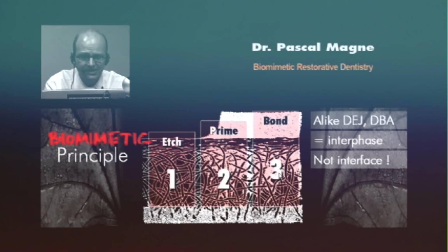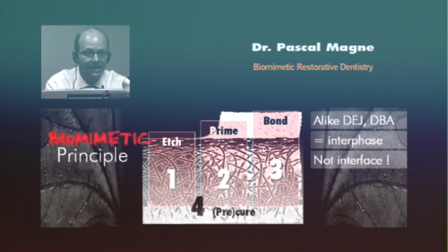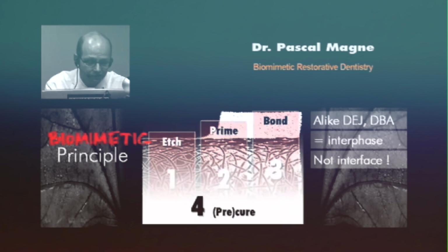Now, you can't mix these 3 in the same bottle. Of course, you can, but what you will get is kind of a salad dressing that is not going to work as well as if you use each of these products independently and separately. And there is a 4th step. I told you 4th step. What is the 4th step to successful bonding? It is the use of light, pre-curing the adhesive before you apply the restorative material. When we do direct restorations, we always do that. We pre-cure the adhesive before we actually place the restoration.